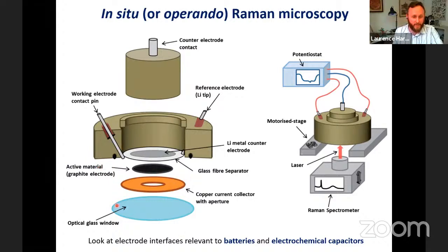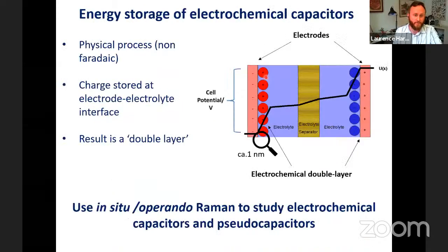And so we were able to form a 2-electrode cell. So here we're getting a little bit closer to an operando condition. We're really looking at a system as a type of coin cell electrode, but we have optical access to that. And then we just mount it on the Raman spectrometer and a potentiostat.